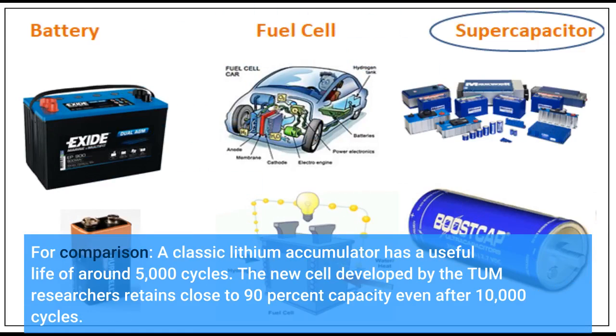For comparison, a classic lithium accumulator has a useful life of around 5,000 cycles. The new cell developed by the TUM researchers retains close to 90% capacity even after 10,000 cycles.